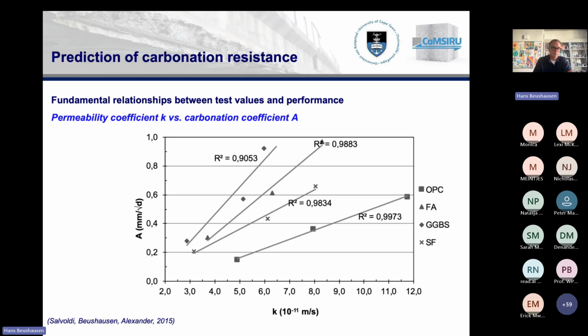For example, here, some research we did at UCT about 10 years ago, where we could link the permeability coefficient to the carbonation coefficient, depending also on the binder type, because essentially carbonation doesn't just depend on the physical pore structure, which is what you measure with the OPI test. It also depends on the chemical makeup of the pore solution. So we could establish for different binder types the correlation between the permeability coefficient, the OPI value, and the carbonation resistance for your structures in different environments.